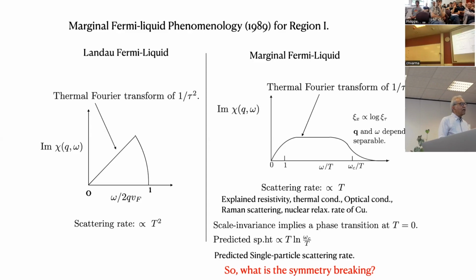Now, we could also predict that the specific heat from that will be not linear in T like in a Fermi liquid, but will go as T log(omega c over T), or thermopower will also go as T log T. Specific heat behavior in the cuprates has been only measured in the last 3 or 4 years. The group of Thomas Klein at Grenoble on samples by Louis Taillefer in Sherbrooke, and this thing is found.